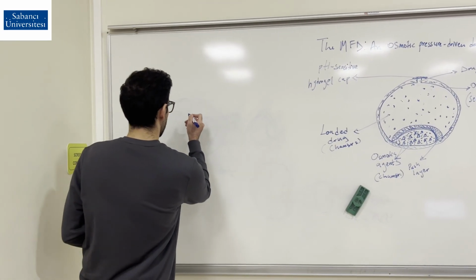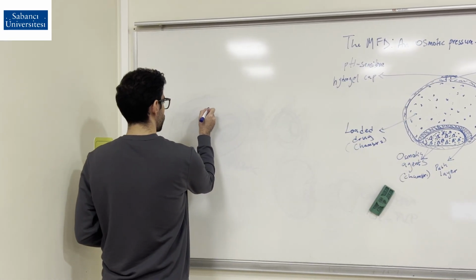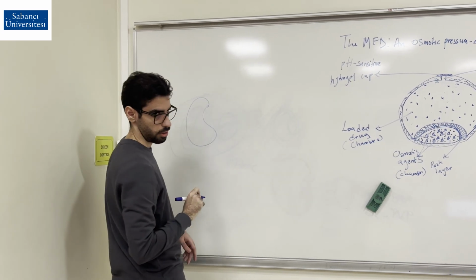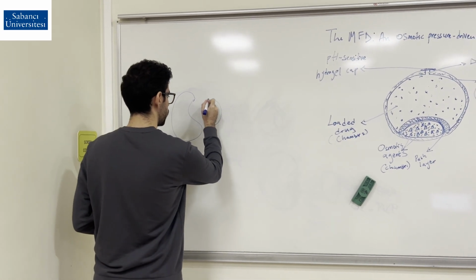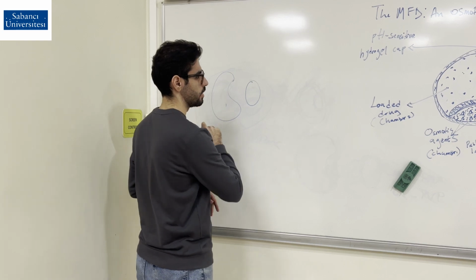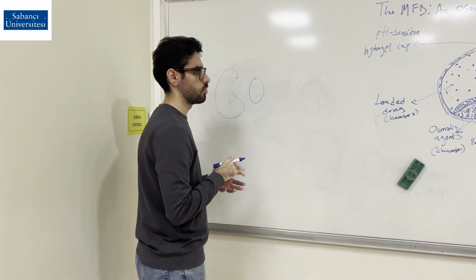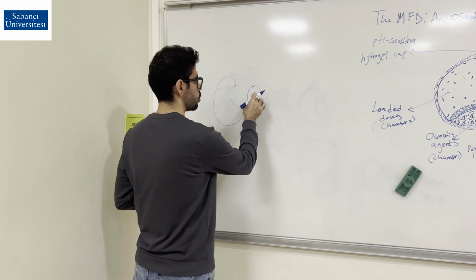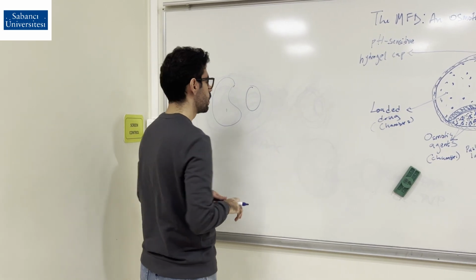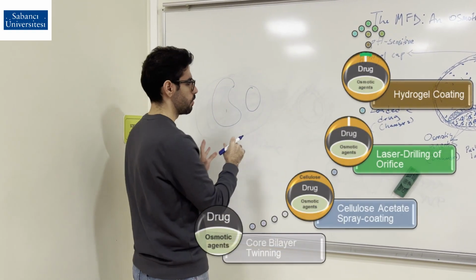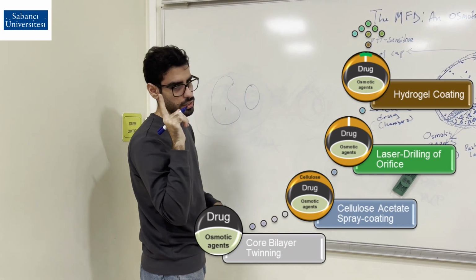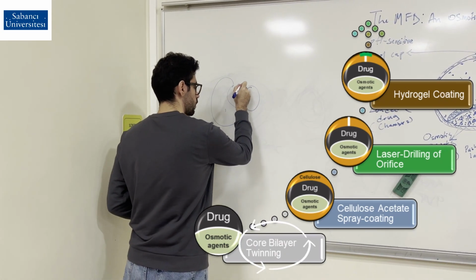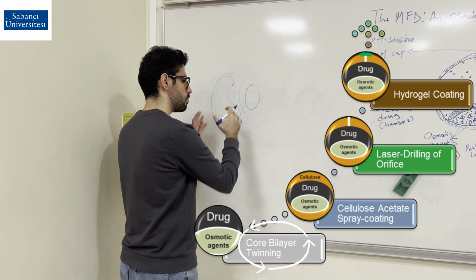As we said, we have two chambers. This is the first chamber. This is the second one. The first chamber contains the drug, which we compress using a granulation process, as well as the second chamber, which contains sucrose and fructose. After we compress them, we bring them together, and we spray HPMC through them, and then we compress them together.